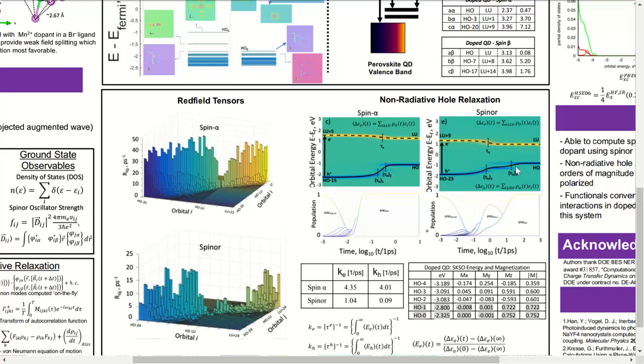So the slow dynamics that you are blaming happens only between the two lowest states, like LUMO and LUMO plus 1. It's the d to d transitions pretty much. And the d orbitals have a spin orbit influence. So if you include spin orbit coupling into the basis, that might make them more orthogonal to each other, or it's a better basis to describe transition metals. It's a really hand-wavy argument, but it's the only one I got.